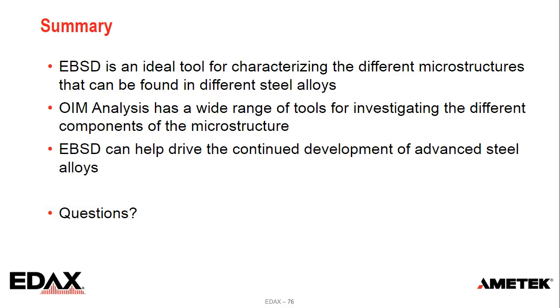Now, we're always a little careful about saying, is an image quality value a definitive number? Can you compare one sample at an image quality of 100 to another sample at an image quality of 100? Generally, we say be very careful of that because there are a lot of factors that can affect image quality. We published a paper about this about 15 years ago, because it can depend on your beam current, your camera settings, your sample preparation. So oftentimes we look at image quality relative within a map. People have done some work trying to standardize and normalize that, but you're looking at a subset. I've also had cases where I vent the chamber and repolish a sample, or rescan it without doing anything else, and my image quality can vary just from that cycle. So you have to control your variables pretty carefully.